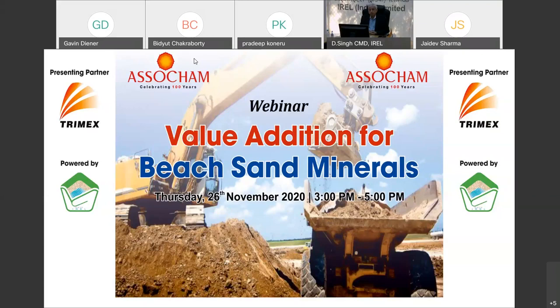My career started in mineral sands with Anglo American, where we were establishing ilmenite smelters on the west coast of South Africa, and we couldn't access Rio Tinto's technology, so we had to go to prevent legal action. We had to move completely away from anything that Rio did. So instead of doing rectangular AC furnaces, we did circular DC. It had never been done in mineral sands before. We researched it and proved it up at Mintek in Johannesburg, and built some smelters, one to start with, and then a second. And then that technology was used on the East Coast at KZN Sands, and now Tronox is a very successful global producer.